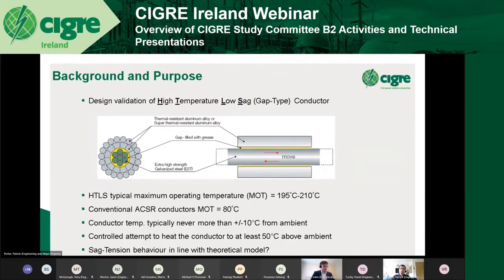So the high temperature test, really what we were doing was a controlled attempt to heat the conductor on a line to at least 50 degrees Celsius above the ambient. And in doing so, we wanted to monitor and assess the sag tension behavior and determine whether that behavior was in line with the expected theoretical model. So those last two bullet points are a good summary of what the test was and what it was hoping to achieve.